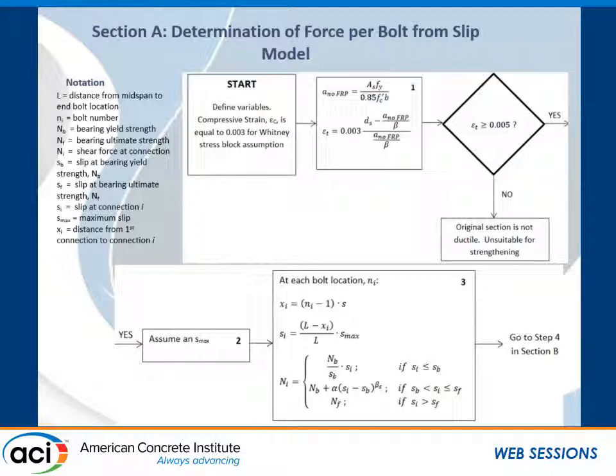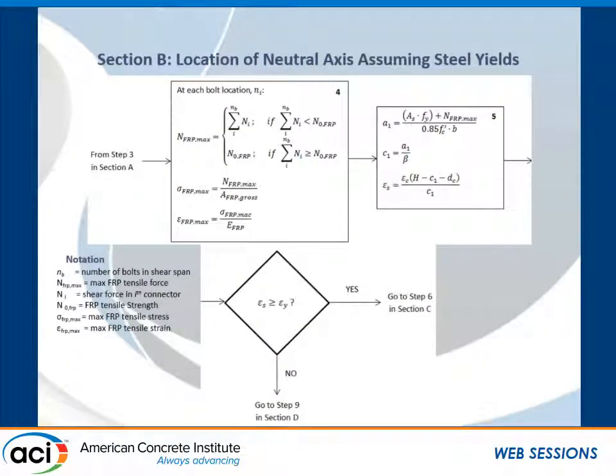We started by confirming that the section to be strengthened qualifies as a tension-controlled section, and then a maximum slippage is assumed, and the slip at each of the bolts in the shear span is calculated, assuming that linear variation. And then at this point, we bring in the bearing slip model that we developed for the anchor bolts to determine the force that we have in each bolt. The maximum tensile force in the FRP is then determined to be the lesser of either the summation of the force we're getting at each of the anchor bolts in the shear span, or the ultimate tensile strength of the FRP. And if the latter is the case, then the failure mode will be by FRP rupture.